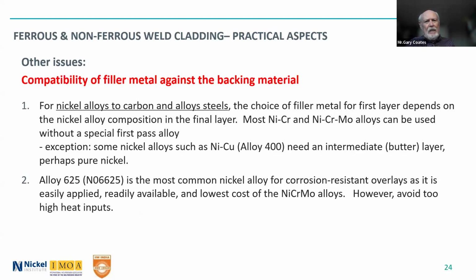For nickel alloys to carbon and alloy steels, generally you don't need a special intermediate first layer there. You most often use the nickel alloy that you're working with. There are exceptions to the rule, as we all know in welding. So the nickel copper alloys, you do need an intermediate, we sometimes call it a butter layer, perhaps pure nickel, perhaps another nickel copper alloy. And that information is in the literature, what to do there.